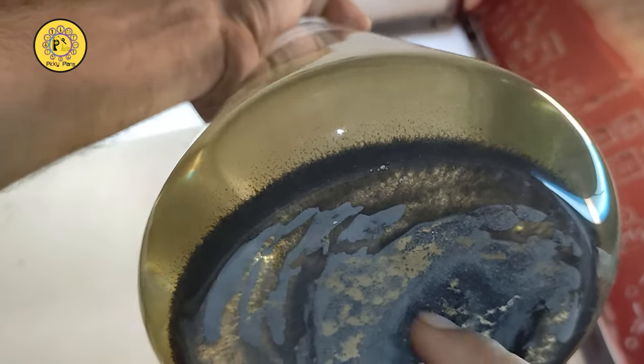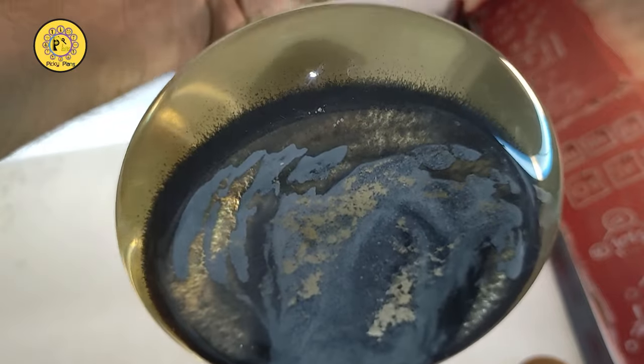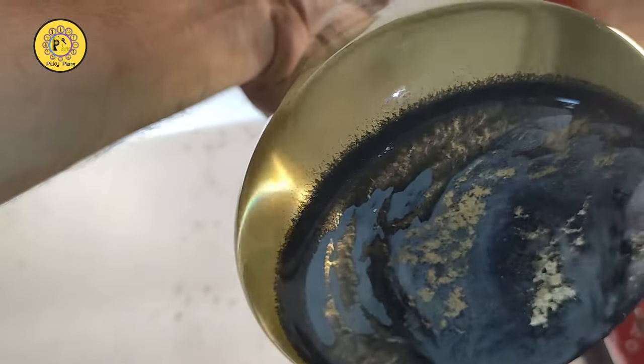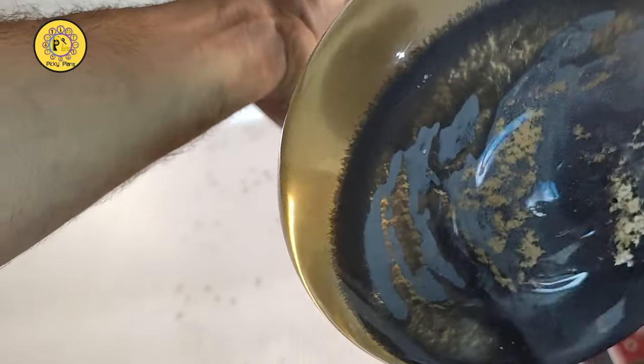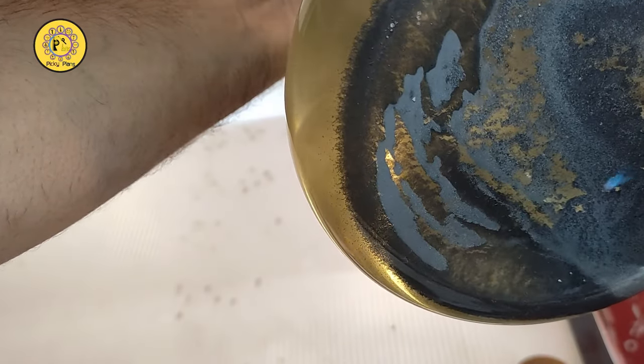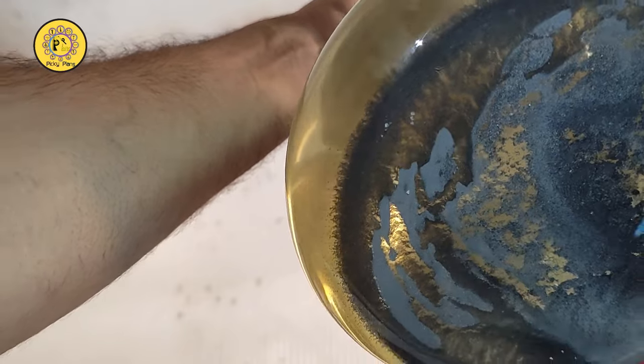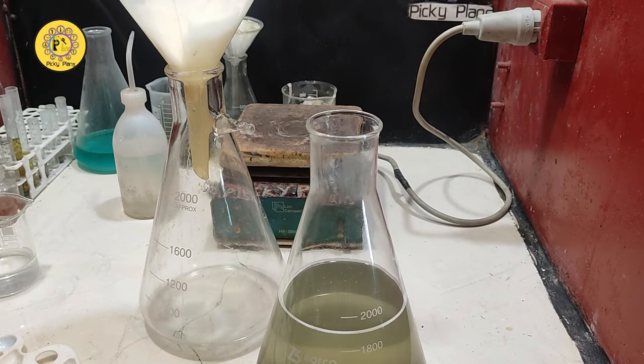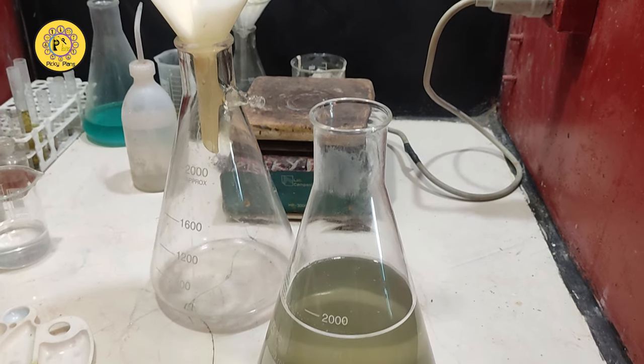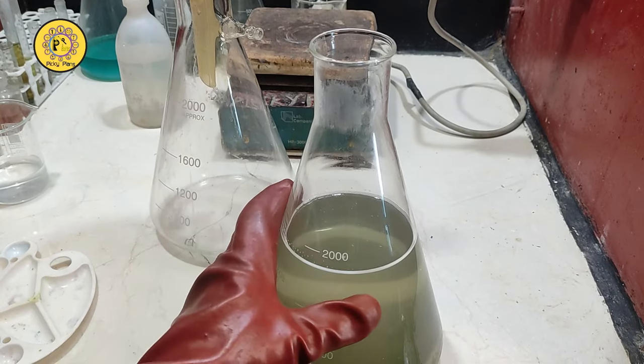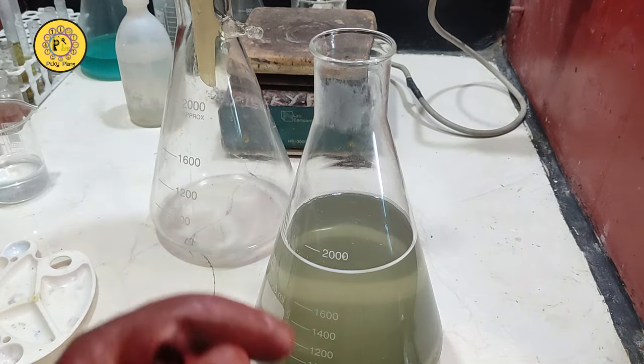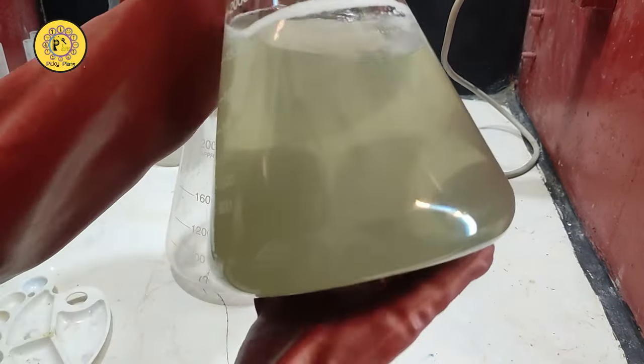Let me show you something interesting about zinc cementation. You can see the fresh zinc color. It has a silvery appearance and is much denser than that black stuff here. Actually, the black stuff here is the zinc which gold cemented on, and it turns to a fluffy form. I let the solution stir with the zinc powder for 1 hour, and I added 3 grams more zinc powder, and now I let this settle down as much as possible. Still there is some zinc and gold suspended in the solution, which I'm going to filter and recover later from the filter.